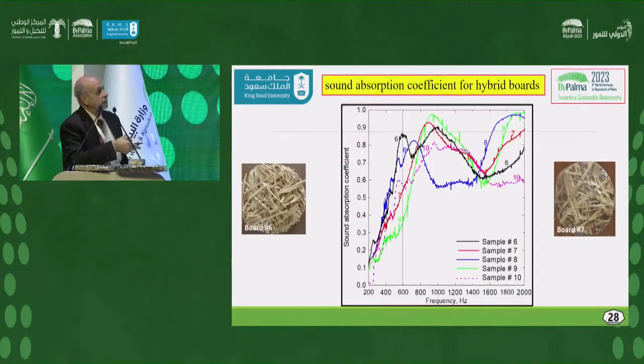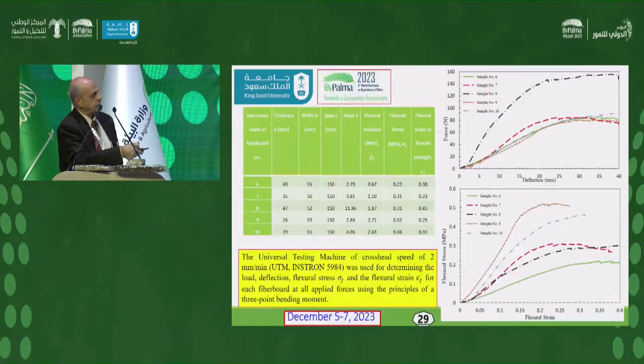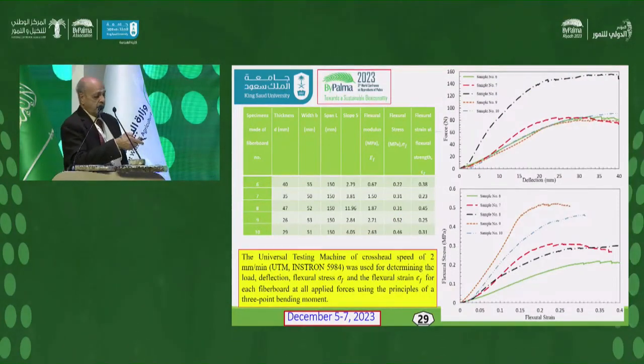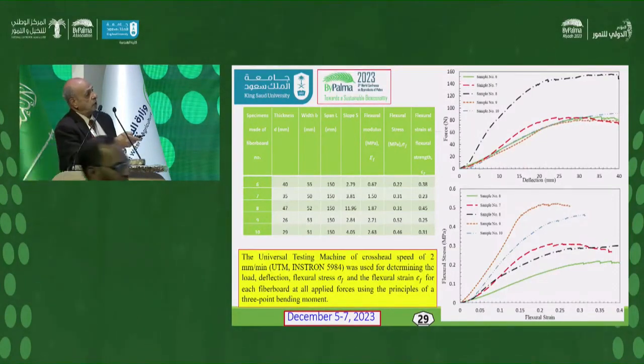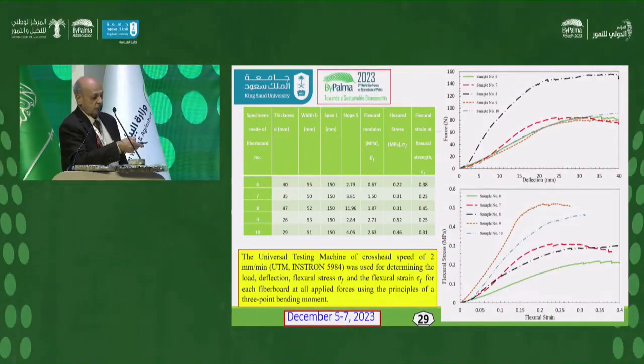This is the sound absorption coefficient for the hybrid one using the palm tree leaves. Okay, as we see, most of them are in this range, which is the communication range of sound, so it is very good at most frequencies. It's higher than 0.5 for most samples. This is the 3-point bending, okay, which has been done for the hybrid sample, and this is the Young's modulus and the stress and the strain using the universal testing machine.